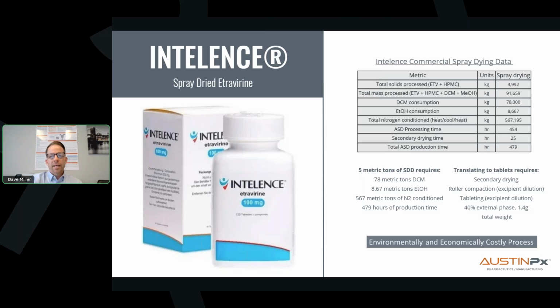this material, and conditioned, meaning it's got to be heated to evaporate the solvent, cooled to knock out the solvent, and then reheated as it re-enters the process. So if you add that recycle of nitrogen through the process, it's a substantial mass of process gas that's being continuously conditioned, which is a good indicator of the energy consumption. The total processing time to produce 5 metric tons of ASD by this process is about 480 hours.